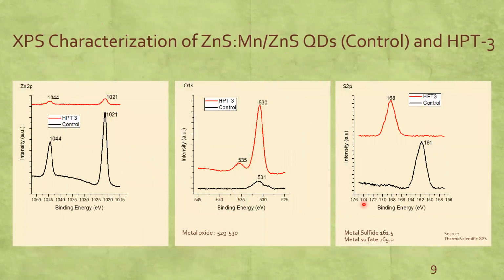So here are the XPS data. We're looking at zinc, oxygen, and sulfur peaks. Both zinc and oxygen show similar peaks in both control and HPT3 samples, but there is a pronounced difference in the sulfur peak. We compare the peak to the binding energy values obtained from the Thermo Scientific XPS database. The peroxide oxidized sample shows a sulfate peak at 168 electron volts compared to the sulfide peak at 161 in control. Therefore, we confirm the oxidation of sulfur into sulfate with peroxide oxidation.